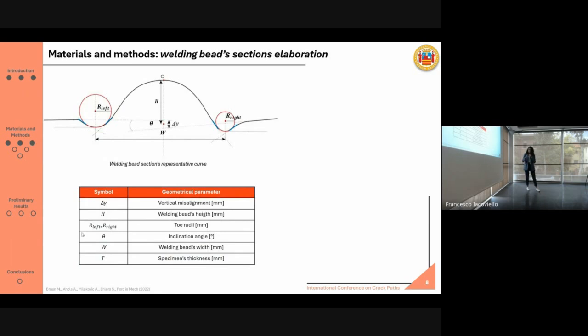So what we did basically was study the section curve for the specimen near the welding bead, and we tried to evaluate these geometrical parameters that are summarized in this table. So we have the vertical misalignment, the height of the welding bead, the radii at the toe, both left and right, the inclination angle, the welding bead's width, and the thickness of the specimen itself.